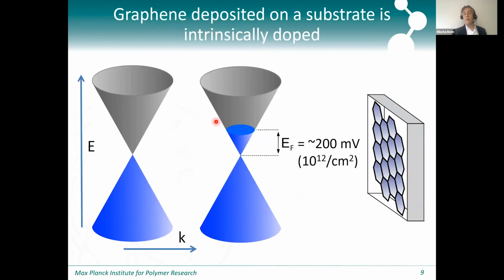Now, graphene, if you're going to make a device, you're not going to have freestanding graphene. It's going to be on a substrate. And if you put it on a substrate, you shift the Fermi level up or down, depending on the nature of the substrate, and you typically get a shift of the Fermi level by about 200 millivolts, which corresponds to a carrier density of about 10^12 per square centimeter. So this is important to keep in mind: graphene is a semi-metal, but it is actually conducting when you put it on a normal substrate, because it gets doped.